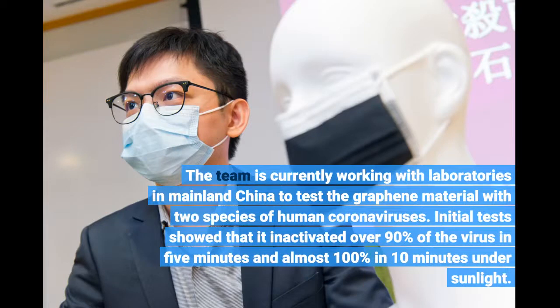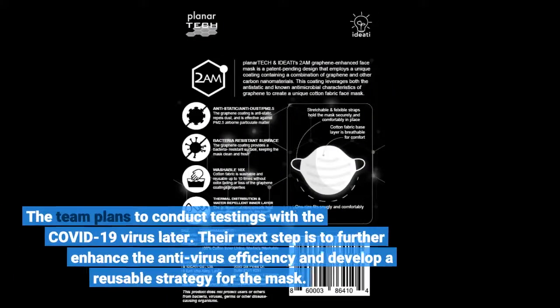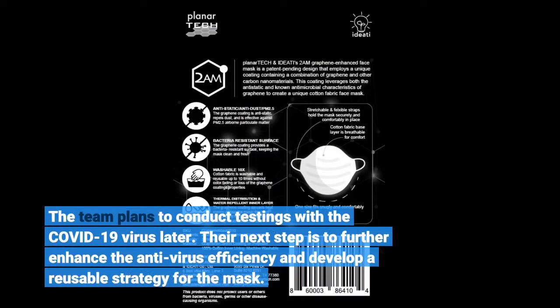The team is currently working with laboratories in mainland China to test the graphene material with 2 species of human coronaviruses. Initial tests showed that it inactivated over 90% of the virus in 5 minutes and almost 100% in 10 minutes under sunlight. The team plans to conduct testing with the COVID-19 virus later.